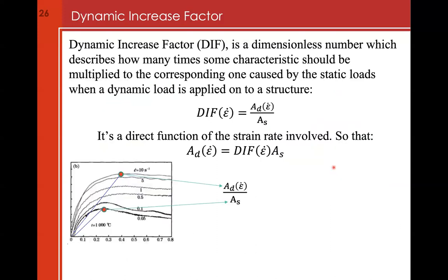For practical applications, we define the Dynamic Increase Factor (DIF), a dimensionless number showing the ratio of a quantity measured under dynamic conditions at a certain strain rate, non-dimensionalized with respect to the same quantity under quasi-static conditions. This is very important because you can obtain a dynamic characteristic for a certain strain rate by multiplying this coefficient by the static value — for instance, the stress evaluated under dynamic vs. static conditions in the stress-strain curve.